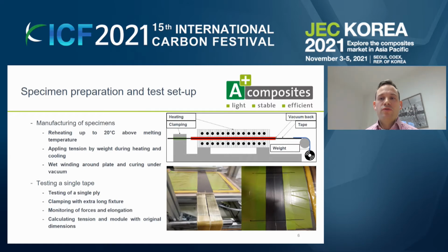We tested all specimens on a single ply, so we make a single tape or a single tow or a single prepreg test. For thermoplastics, we reheated the material to find out how much loss will occur when you apply a tension or apply a vacuum, or if you reconsolidate the material, like for injection molding processes. And for wet winding, we wind up the material around a sheet, and we applied a tension, which is about 50 newtons per roving, and we cure them under vacuum, which is the standard test for investigating the strengths. And I have to point out that we monitor the loadings, not the strengths, and we monitor also the elongation to calculate the Young's modulus.